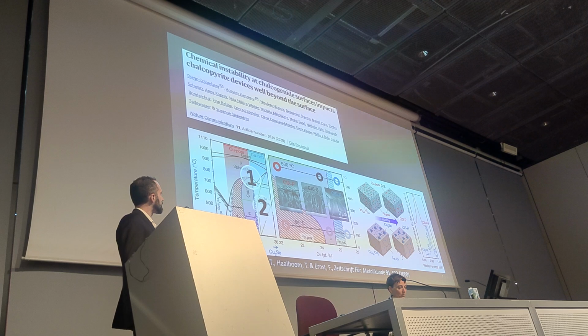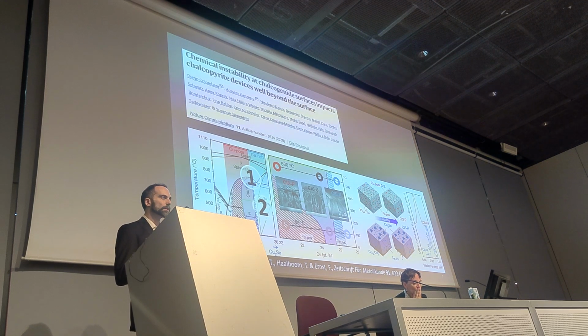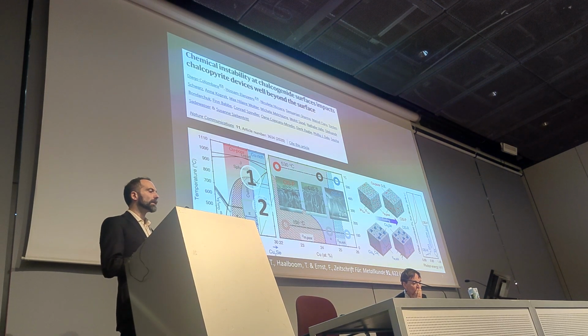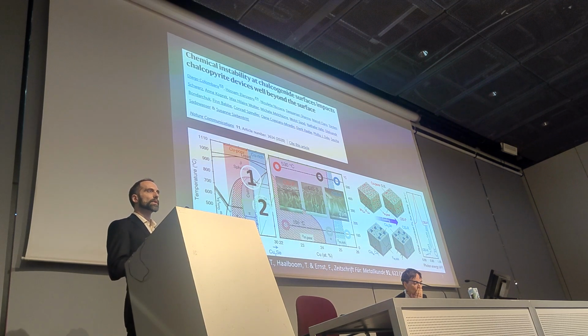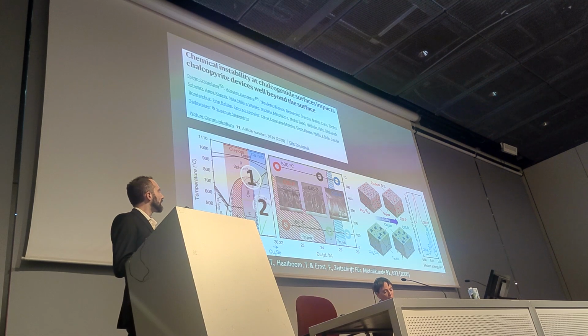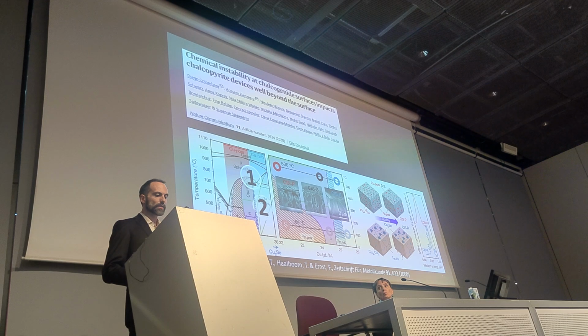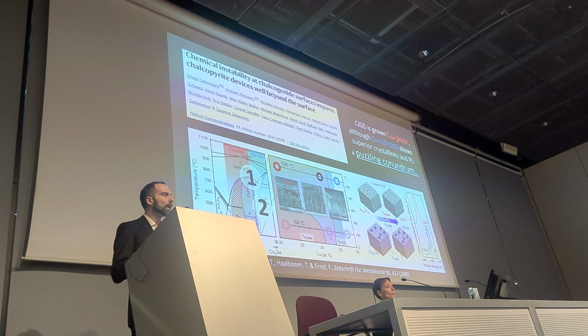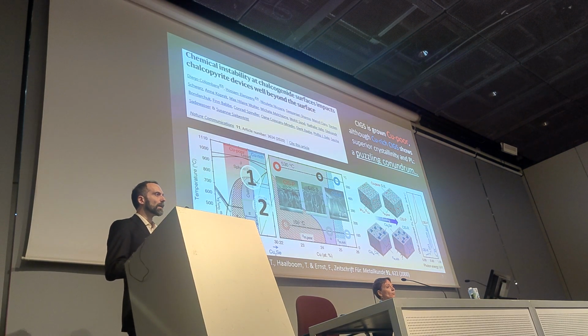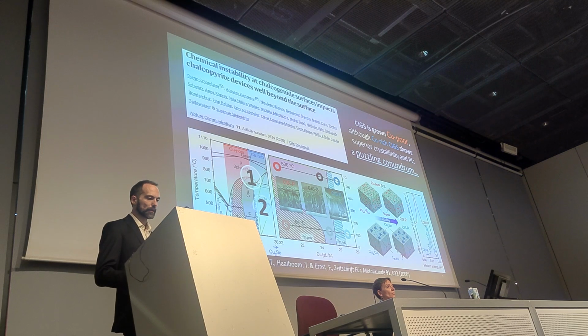But the copper rich phase, the copper selenide that forms when you grow copper rich, that is a killer, because copper selenide is a conductive phase. So whenever you have copper selenide, unless you remove it, you don't get any working devices. The thing is, it's not the main reason why the copper-rich material doesn't work well, because if we do remove the copper selenide, we still get working devices, but they are not as good as the copper poor. So what is going on? This is a puzzling conundrum that kept the community studying for quite some time, and we had to unravel it.